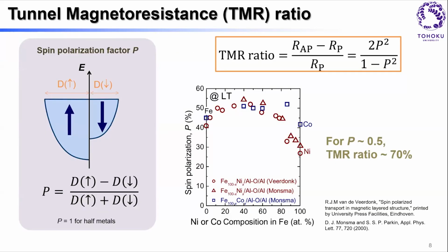Okay, the first one is resistance change. Parallel and anti-parallel configuration. When tunneling is not coherent, random tunneling, then it can be described by the density of states at the Fermi edge, and it's given like this. And if you plug in all the numbers for, let's say, iron or cobalt or nickel alloys of them, the maximum spin polarization is about 50%, which means that your tunnel resistance change is 70%, meaning that if you have a 1 kilo ohm resistor, you can make it 1.7 kilo ohm.